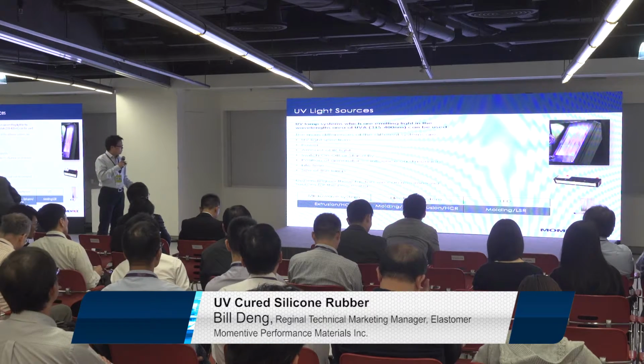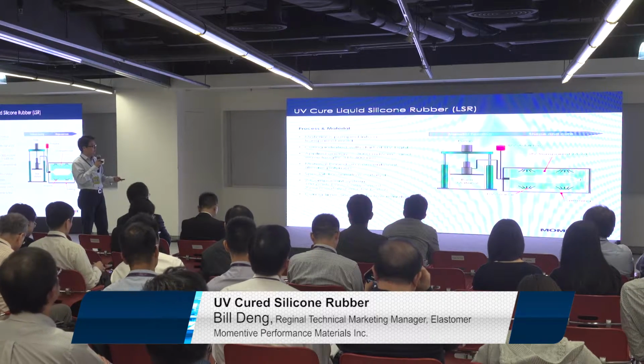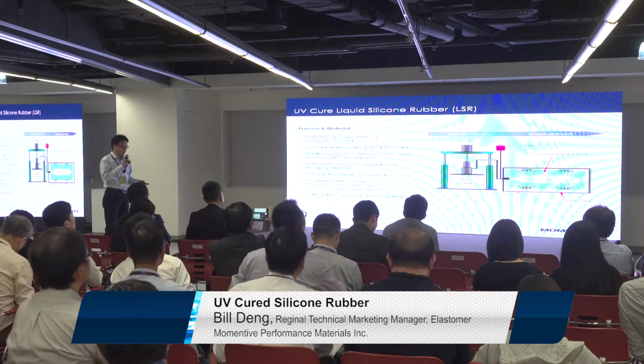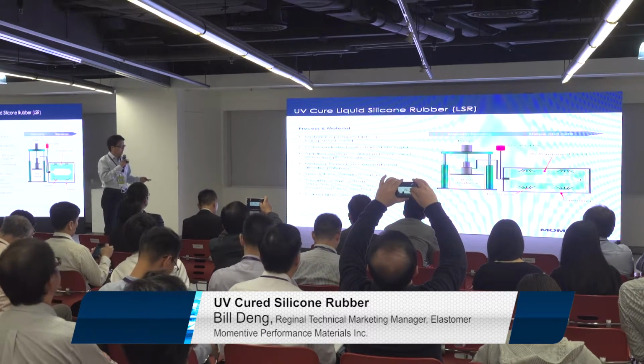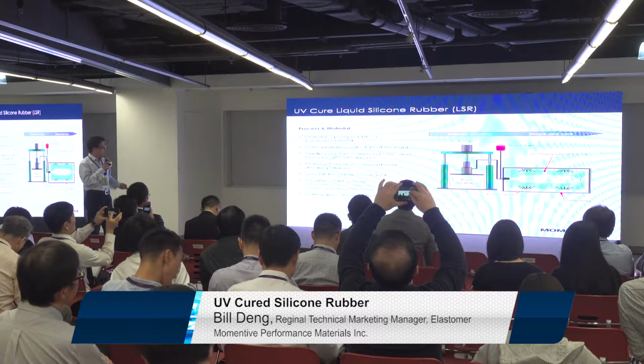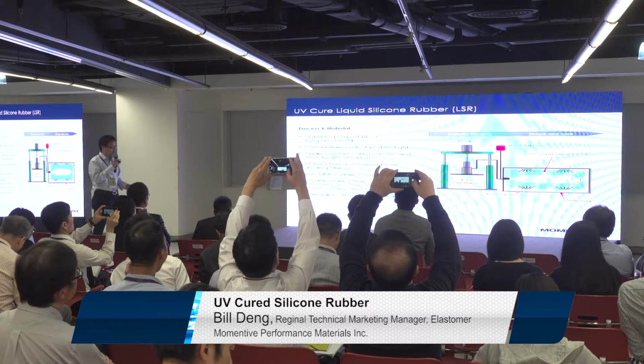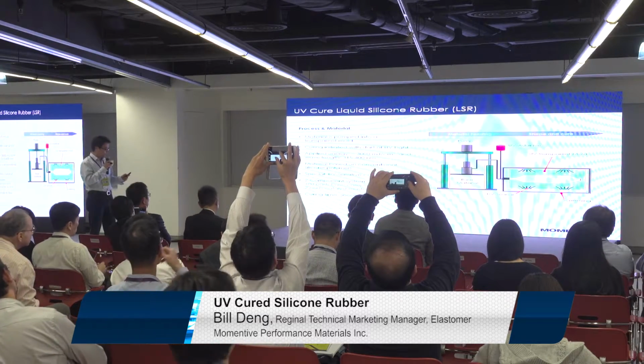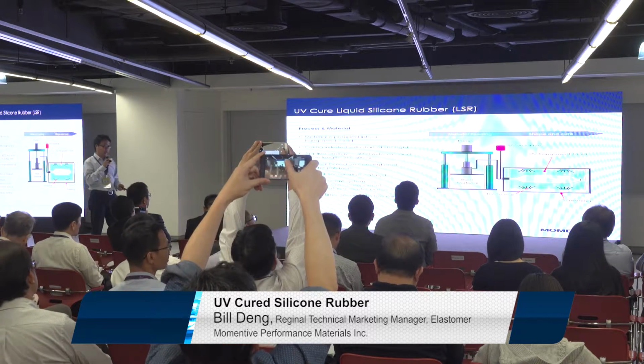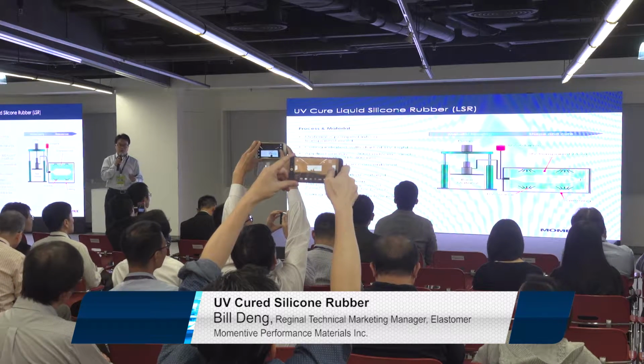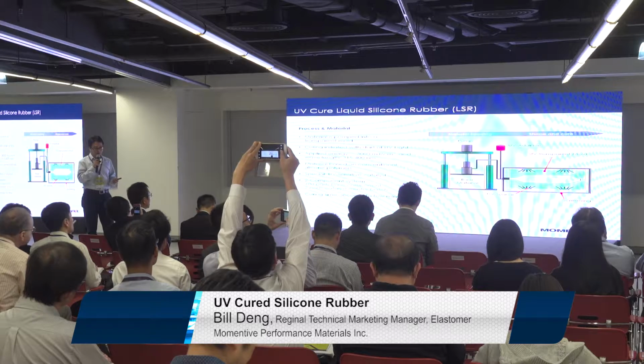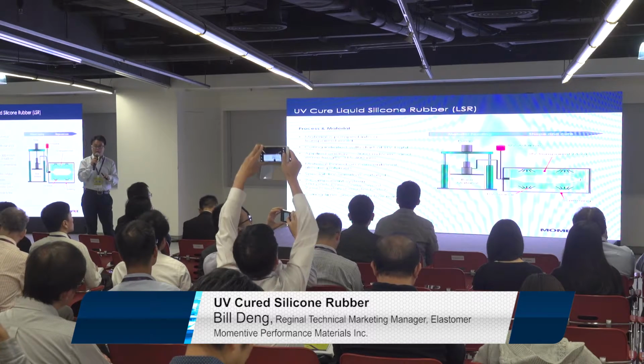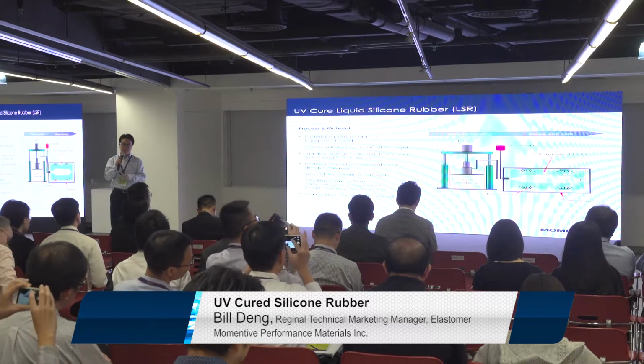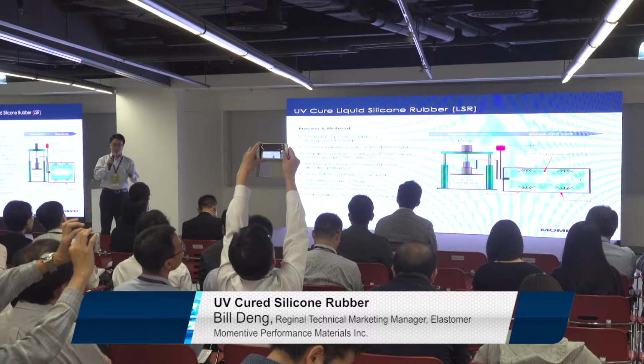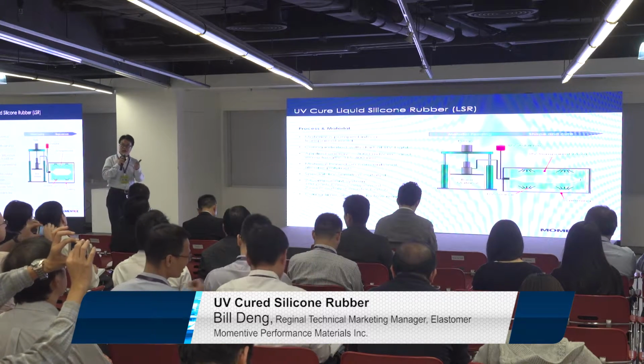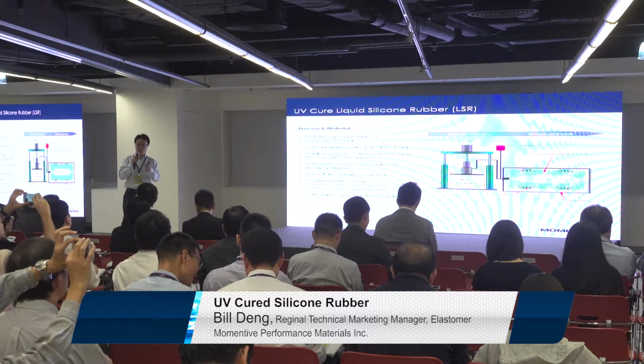So this is a very simple legend for how UV silicone rubber, actually liquid silicone rubber, works. Because we still use the traditional LSR injection molding machine. The only difference is, first, the material system. Because as most people here, if you touch LSR or are familiar with LSR, you know in a traditional LSR injection molding machine we have A and B parts, right? So A part contains catalyst, B part contains cross-linker. So you use a pump to pump both parts into the static mixer, get them to be a very even system and go into the mold, right?